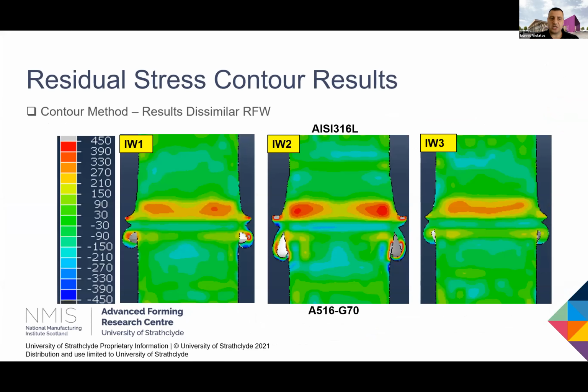As a summary slide of what we have measured, we can see the three different trials and the residual stresses being generated due to these trials. In the first one, stresses are mostly concentrated in the stainless steel. There is some compressive layer between the two materials because of the mismatch of Young's modulus, and obviously because of the different deformation that these two materials are exhibiting. With higher forces and higher pressure, we exhibit bigger, tensile stresses, obviously.